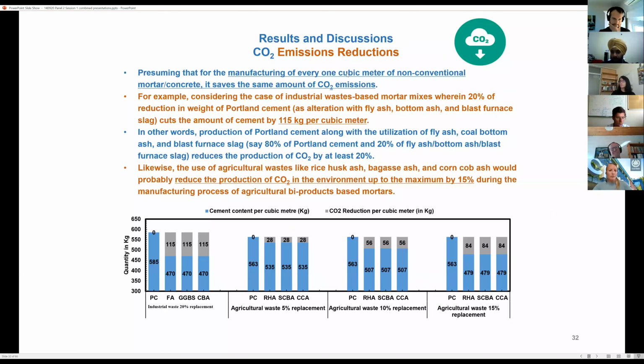Coming to the carbon dioxide reduction, or the calculation part. Per cubic meter of the mix, we initially used 585 kg of cement, but after replacing 20% with the industrial byproducts, we reduced the carbon dioxide emissions by 115 kg. Likewise, for agricultural byproducts, we have reduced the carbon dioxide emissions by 5%, 10% and 15%. These values have been calculated according to simple calculations.